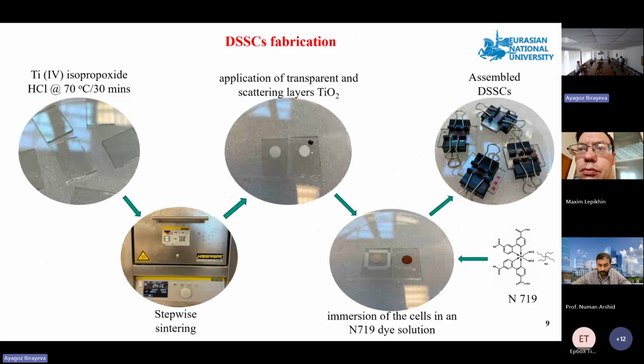The photoanode was prepared on FTO by deposition of compact, transparent, and scattering titanium dioxide layers, followed by drying and sintering. After cooling, the titanium dioxide film was soaked in dye N719 for 24 hours and then rinsed. Finally, the counter electrode was assembled using double-sided tape as a spacer, and the iodide-triiodide electrolyte was added between the electrodes.